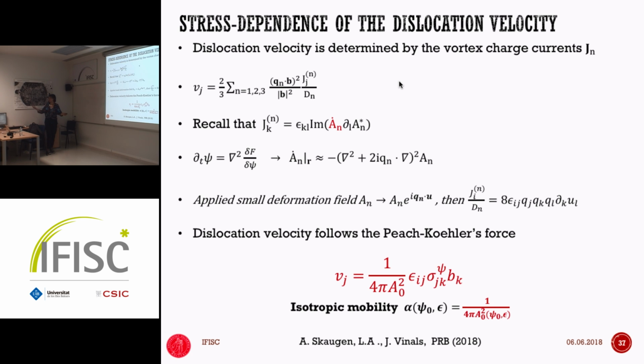So I can use the linearized approximation and say that to the leading order, it's driven by this gradient operator, which means that if I now say that this dislocation lives in an applied field, this applied field could be imposed by the external boundary condition or by the fact that there's another dislocation somewhere else, right? So if this dislocation is by its own in an infinite field, by definition, it's not going to do anything. It's going to be static. But if I apply a force, it's going to move under the influence of that force, right?